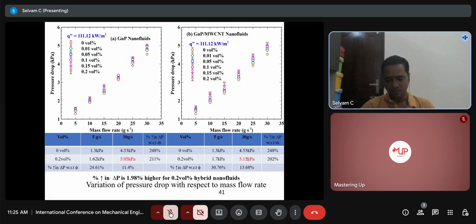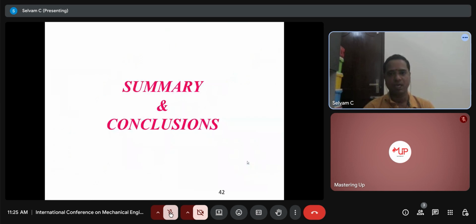Similarly here also, while increasing the heat flux, a pressure drop of 5.05 kilopascal was observed for graphene alone, and 5.15 kilopascal with the use of hybrid nanofluid. And this is the summary and conclusion.